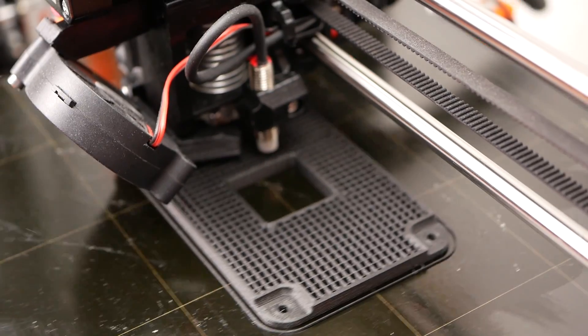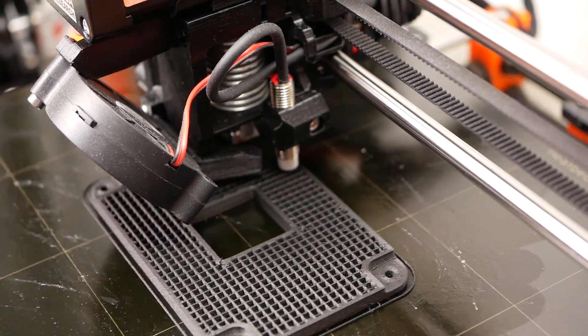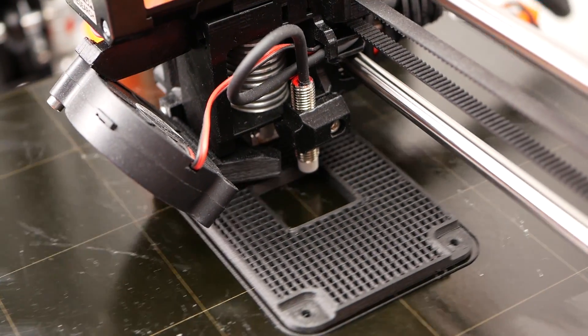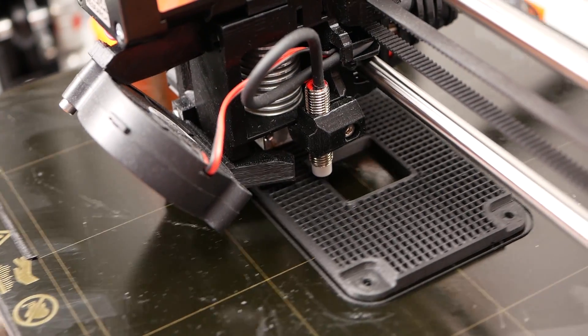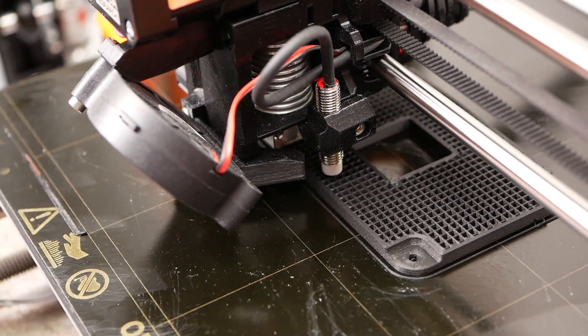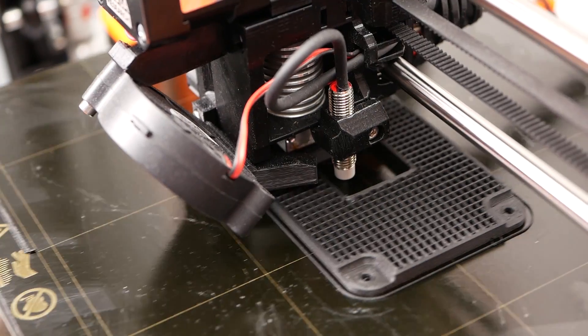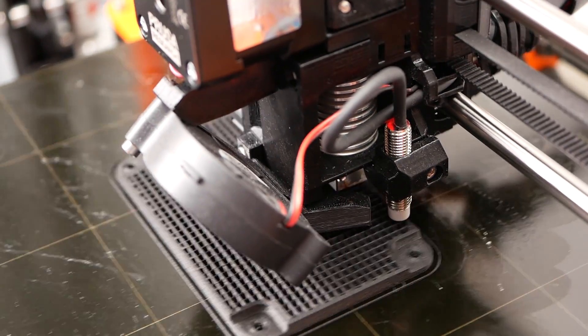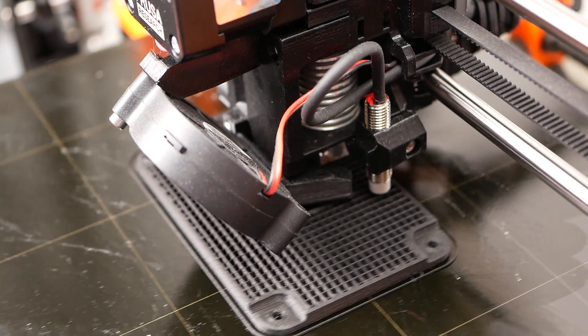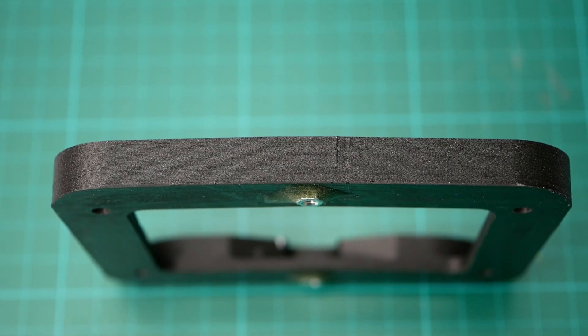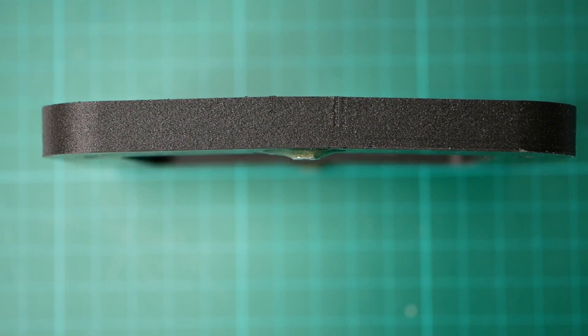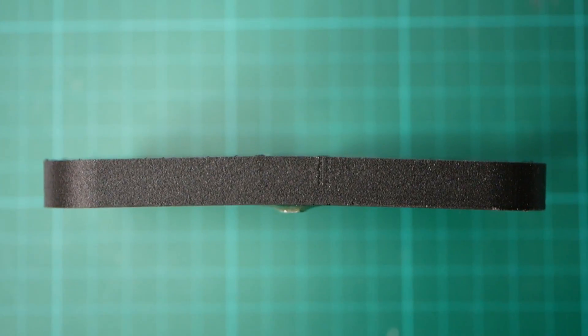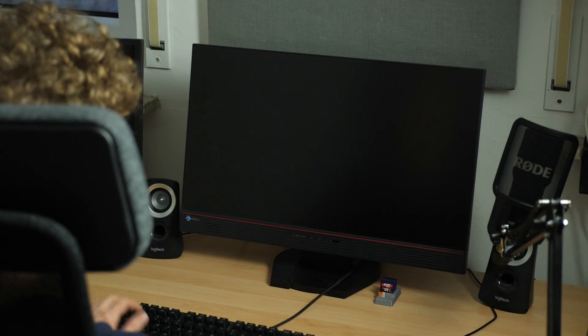The speed of creep is usually dependent on the applied stresses, the temperature and a couple more. So even though the temperatures were far away from the melting point of the material and probably not yet at the glass transition point, this permanent deformation happened over the course of a couple of days until the clamping force between the CPU and the cooler was too small and they separated. You know the rest.